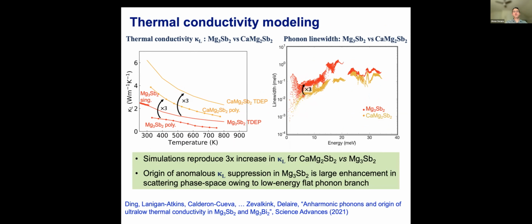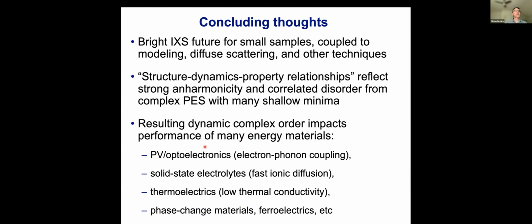So these line widths are still not that high, so it's hard to really capture this with HERIX, I would say. But the effect is already well understood at the level of the phonon dispersions themselves, and the phonon dispersions are actually quite important to understand the scattering phase space. So what are the allowed phonon-phonon coupling terms and scattering transitions? So I'm running out of time.